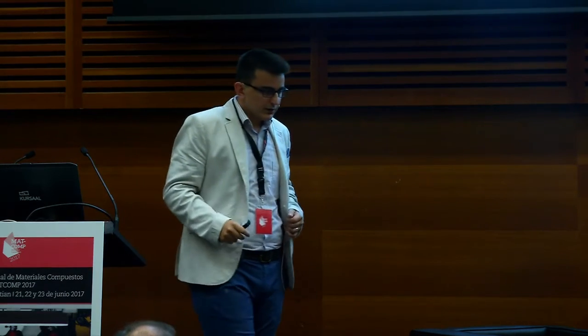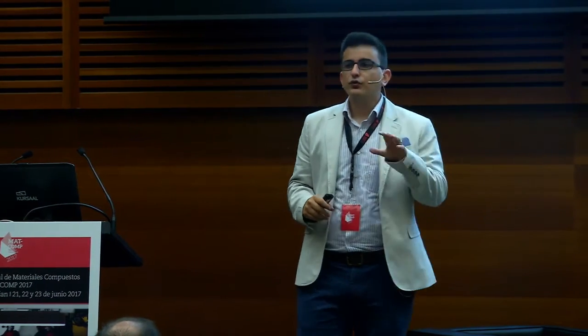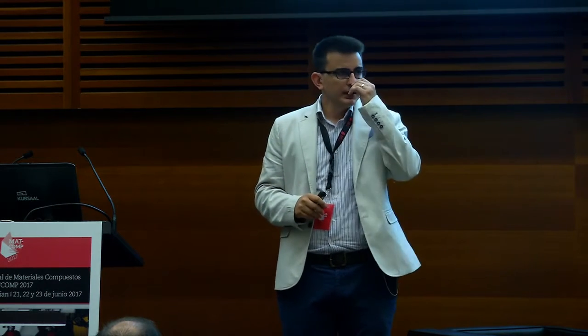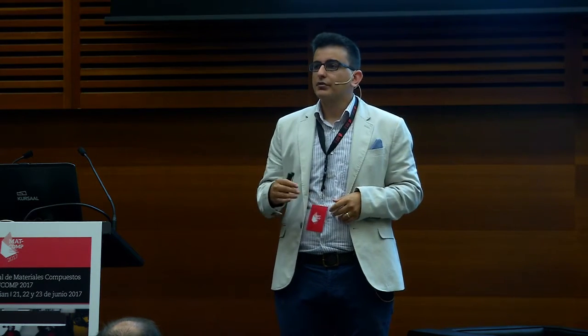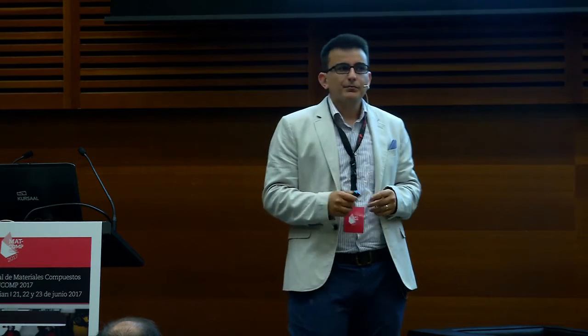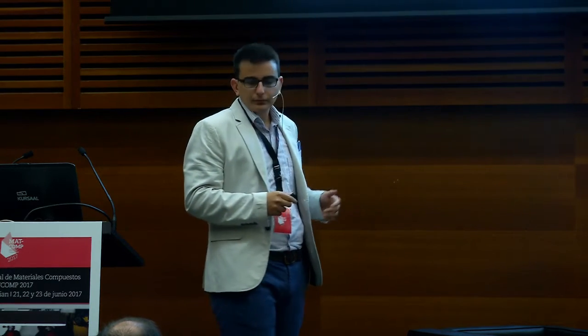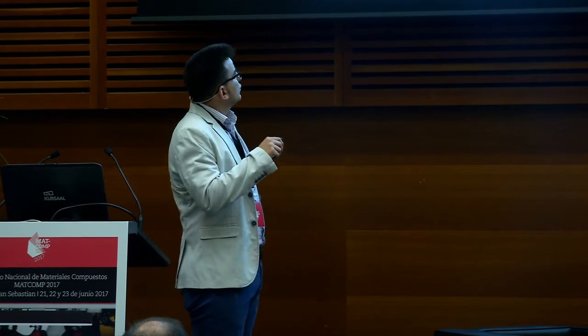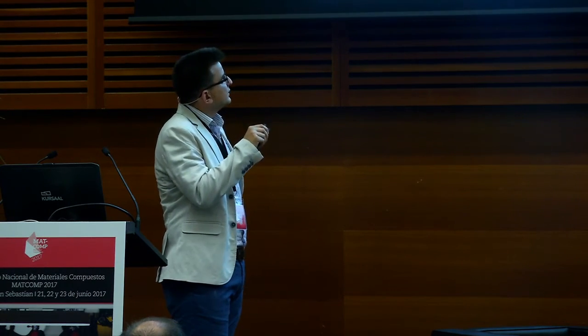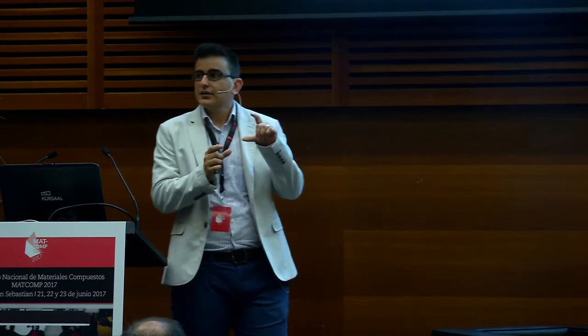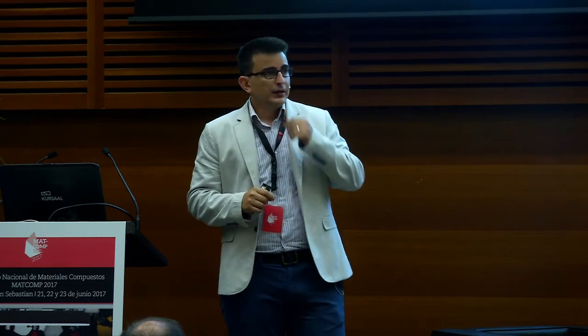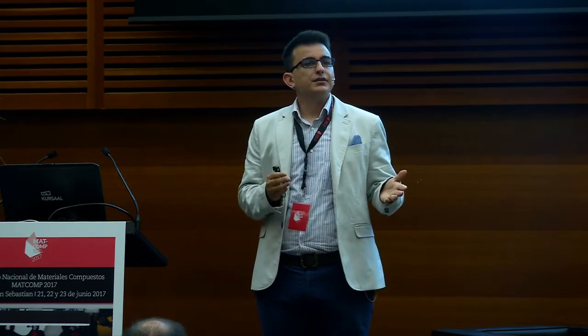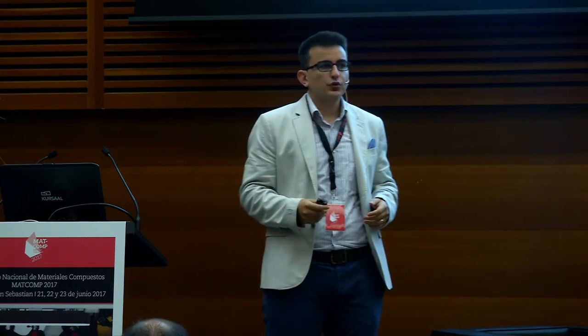Another way to prevent non-uniform curing for thick profiles is using a preheater before the pultrusion die. So let's have a look at an example of a really thick profile, 10 centimeters by 10 centimeters, and let's see the effect of using a preheater on the curing and the residual stress formations.